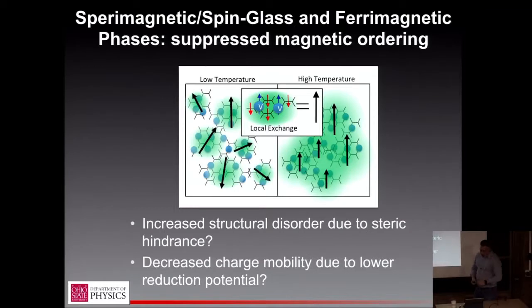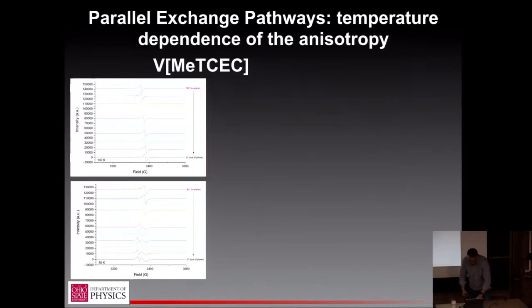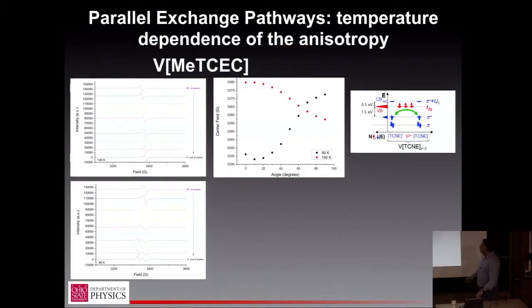But coming back to the FMR data, what I think is happening is that at high temperature, we have a globally ordered film. That means the magnetization everywhere is pointed in the same direction. That means we have significant demagnetizing fields. And we have classic thin film anisotropy that you would see in iron or cobalt or something like that. But as it gets colder, the film is no longer globally ordered. It breaks up into these individual domains with local magnetic anisotropy, which effectively looks like a ferromagnet that's been demagnetized.